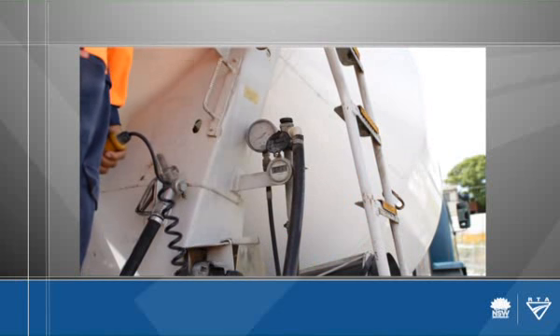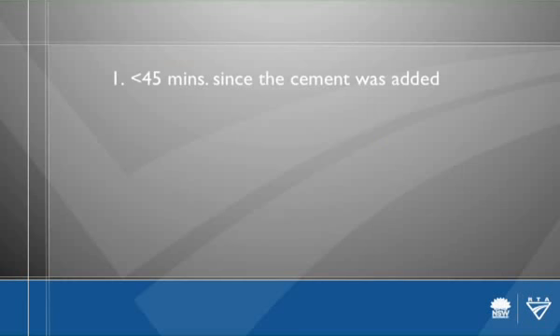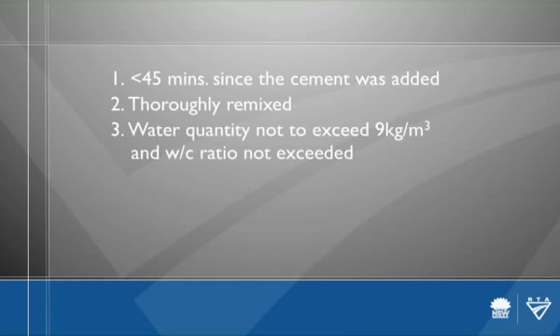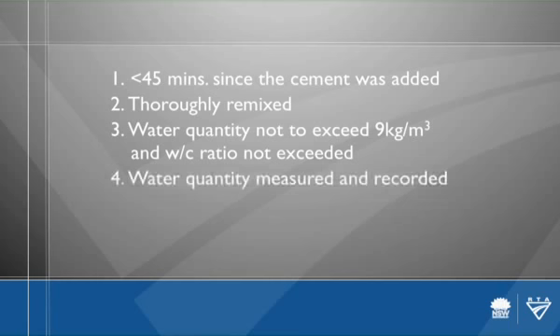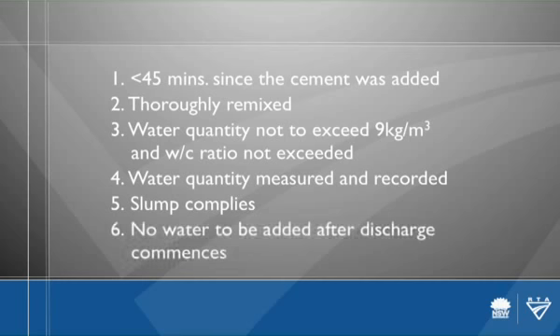And how much can you add? Yes, you are allowed to add moisture. There are a few provisos on that. The first thing is that it has to be within 45 minutes since the cement was added at the batching plant. It's got to be thoroughly remixed on site. And the water quantity is not to exceed 9 kilograms per cubic metre, and the water cement ratio is not to be exceeded. And the water quantity must be measured and recorded, and the slump still has to be within the range required, but no water can be added once the concrete truck starts discharging.